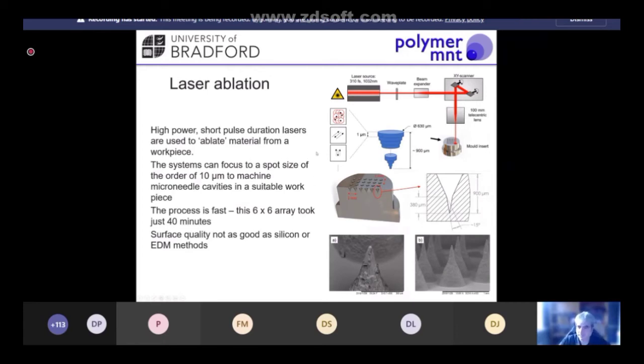Another technique we can use is laser ablation. So we effectively burn our microneedle holes using a very high power short pulse laser. We work closely with the University of Bradford on their laser ablation technology for creating these microneedle structures. By using a scanning technique, we can scan the laser head around our mold insert that goes into our injection molding process. We can make really accurate shapes in this. So microneedle shapes here, we've got an example which is 900 microns high with a base width of about 400 microns. And we get really good creation of these holes to form our microneedle cavities.